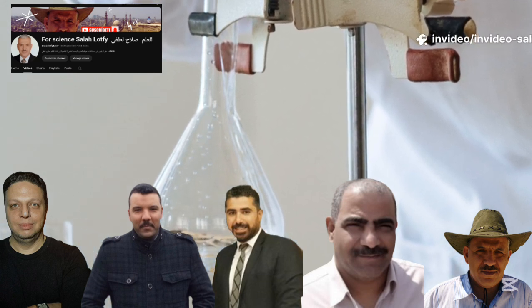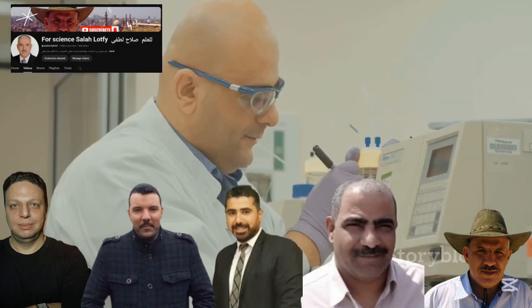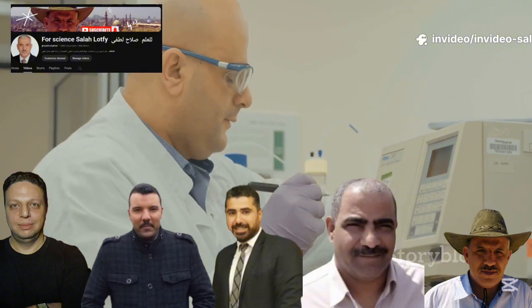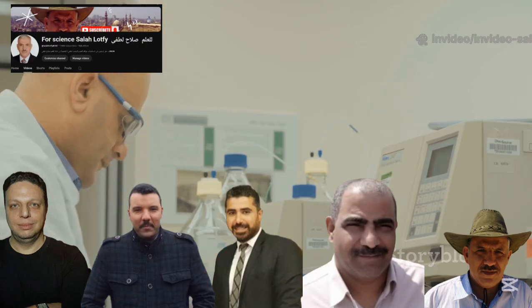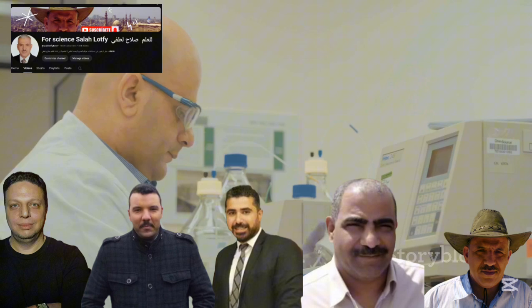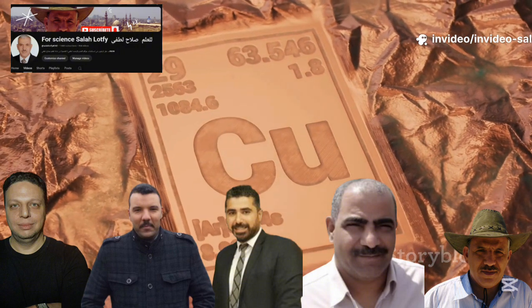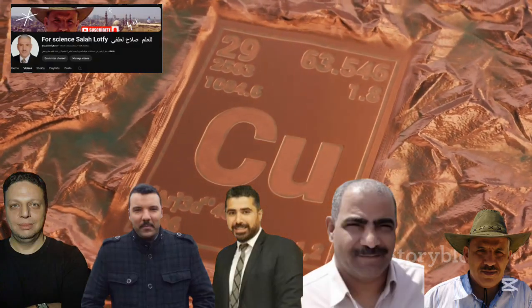copper(II) complex. Synthesizing a new compound is only half the battle. Now we must rigorously prove its identity and structure through a suite of analytical techniques. This characterization process is like chemical detective work, where each test provides a crucial clue. We began with the most fundamental test, elemental analysis. This technique precisely measures the percentage of carbon, hydrogen, and nitrogen in the sample. Our results confirm that the elemental composition matched the theoretical values calculated for our proposed copper complex structure, providing the first piece of evidence that our synthesis was successful.